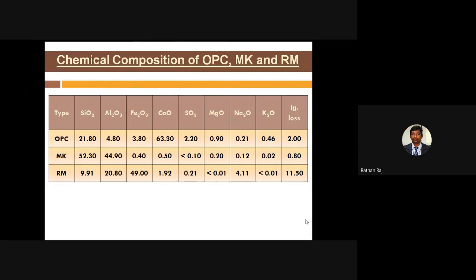As I already told, whatever supplementary cementitious material or replacing material is to be used for the concrete, we should be more concerned about what chemical components are available. For example, in the metakaolin, the silica content is very high, 52.3%. And the unwanted Al2O3 aluminum content is also available. It depends on the variation of the extraction and is also time dependent. At the particular time that amount was very high, and the iron content is very low.